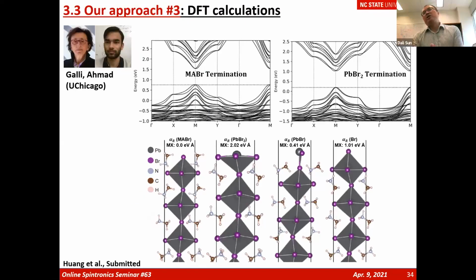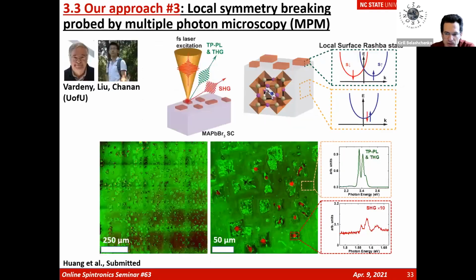Yeah, that depends on the terminations, the organic ligand and the lead exposure. That's the DFT simulation for different terminations with exposure to bromine or lead or lead bromine or maybe more. We can even see water absorption on the surface. That dramatically changes the electronic structure of your Rashba state. Yeah, but close to the beginning of your talk, there were also some with a fraction of an eV band gap, if I remember correctly.